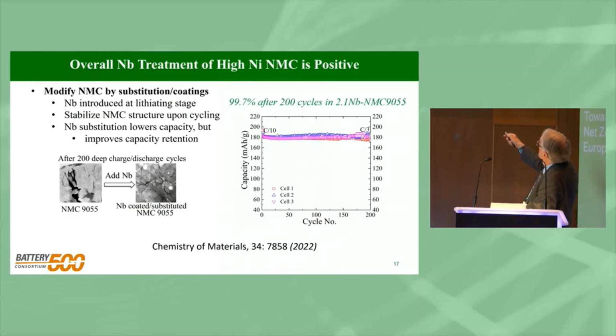So here is a similar plot I showed you before. The capacity we would hope to be up here, but it's down here. It's exactly flat for 3 different cells. So we can reproduce this data that niobium is stabilizing these materials. So it's making these materials viable. And this just got published a few months ago, since your last meeting in Asia.